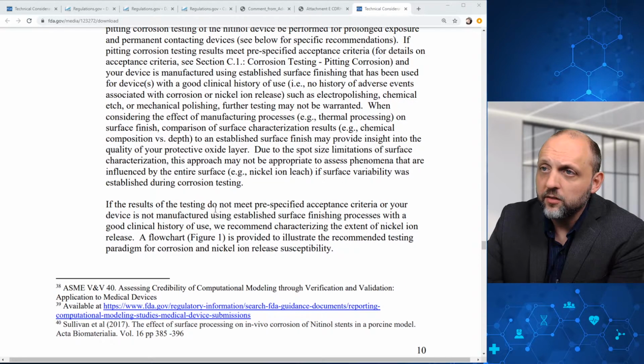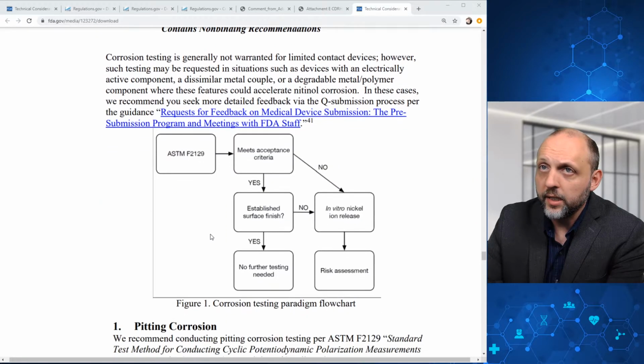And if the results of testing do not meet pre-specified acceptance criteria, or your device is not manufactured using established surface finishing processes with a good clinical history of use, FDA recommends characterizing the extent of nickel ion release. And a flowchart is provided to illustrate the recommended testing paradigm. And here we have this figure.